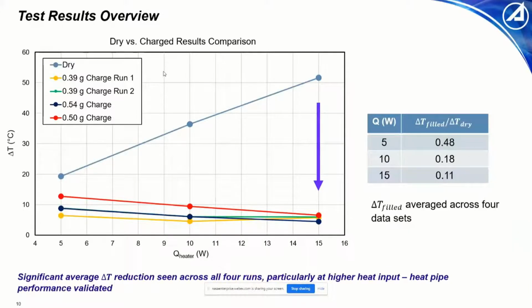A quick overview of our test results. You can see the very top curve here is our dry heat pipe. This data was obtained by powering on a heater at 5, 10, and 15 watts, and no working fluid was present in these tests. This is to simulate a basic spacecraft structure, like a bus panel, without any embedded heat pipes.